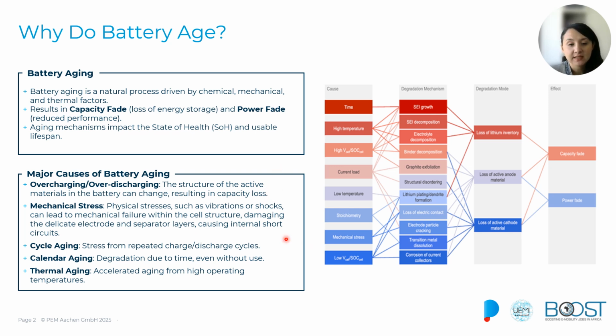Another common reason is the mechanical stress. This can also play a major role in battery degradation, since vibrations, for instance, shock, and the expansion and contraction of the battery cell naturally occur when we are charging or discharging the battery. All of those mechanical causes can cause physical damage in the internal components of the battery, for instance in the electrodes and in the separator, and over time even lead to short circuits and become a risk to the safety of the battery.